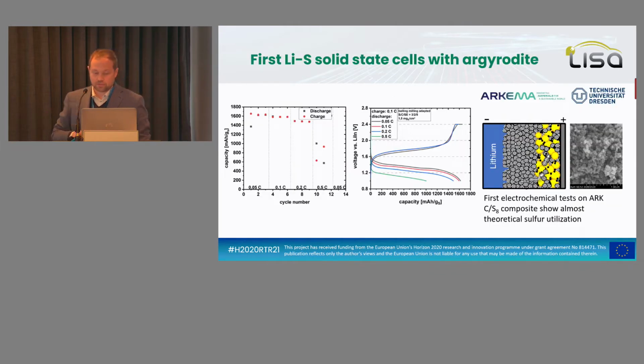This is a solid state battery, maybe one of the first for lithium sulfur at least. Here we can see that we reach almost the theoretical capacity of the sulfur, but it could be that the solid-state electrolyte is also participating in the reaction. But at least this is a kind of first proof of concept without using liquid electrolyte. Here the cell is a pouch cell of 6 ampere hour, and it is a solid sheet of each component, no? Lithium, solid-state electrolyte, and the mix of cathode and solid-state electrolyte. So really without liquid electrolyte.